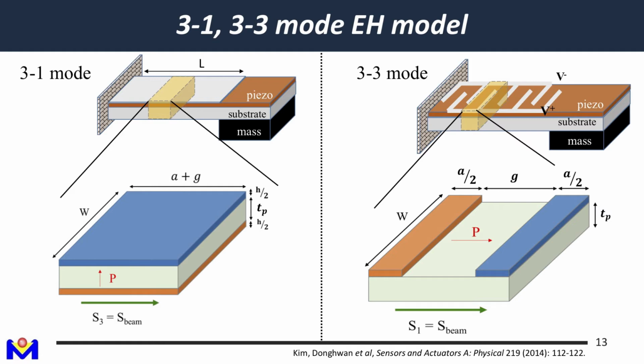piezoelectric constant. So for a simple cantilever structure, if we want to harvest energy in 3-1 mode, it's like a cantilever beam, you have a proof mass, and when you have the vibration excitation, the proof mass will move. You will bend the beam, and because of the bending of the beam, the stress fields will be in the beam axis. And if we have a bottom electrode and top electrode, the electric field will be perpendicular to the stress-strain fields. So this is the 3-1 mode we just mentioned.